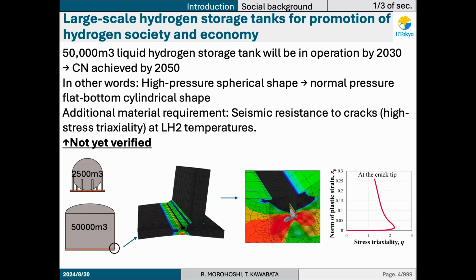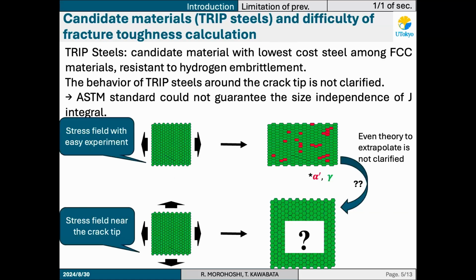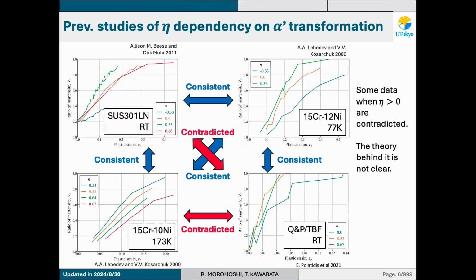However, we couldn't finish it yet. We see that steel with transformation-induced plasticity is a good candidate for this project. However, there's a big problem, which is that we couldn't understand the behavior of the TRIP around the crack tips. That means that a standard like ASTM could not guarantee the size independency of the fracture toughness. So obviously it's a big problem.